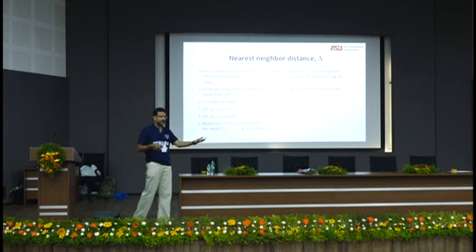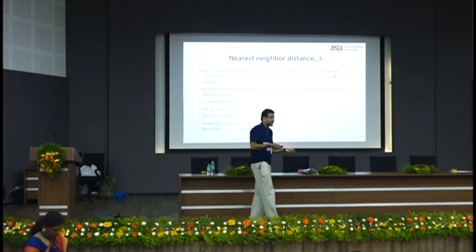Again, simple mathematical calculations to find out spacing between those points, nearest neighbor distances. Very important, right? If I have a cement particle and a limestone particle in the system, if my limestone has to act as a nucleation site for the cement, the limestone cannot be far away from the cement, right? The limestone has to be close to cement, pretty much touching the cement if it has to be a nucleation site. So nearest neighbor distances will become very important.